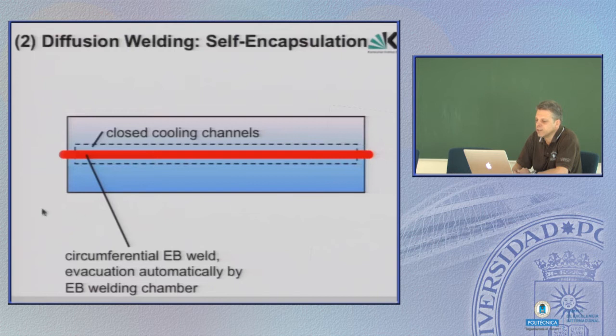The ends are closed, and then you could also put both plates together, and perform a weld around those two plates and do this in an electron beam facility, which works already in vacuum. Then you have an automatic degassing of the whole thing, and it's completely tight welded in vacuum. So you could put this piece directly in a HIP, and thereafter you cut the end through, and then again you have your channel.